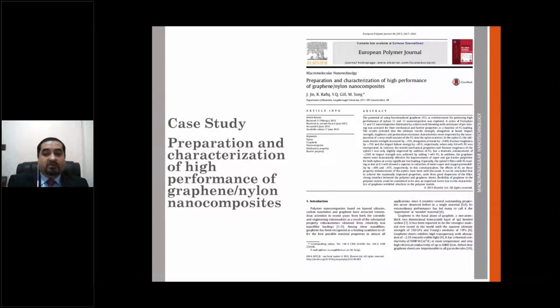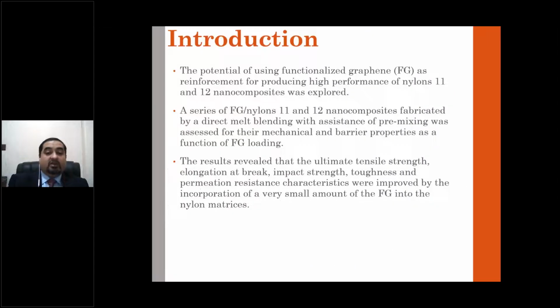Now, another work that has been done by myself in this area is for the high performance graphene nylon nanocomposites. In this area, we were able to develop nylon 11 and nylon 12 functionalized graphene nanocomposites to see what sort of effect it would have on the ultimate tensile strength, elongation at break, impact strength, toughness, permeation resistance, by incorporating as low an amount of functionalized graphene as possible.